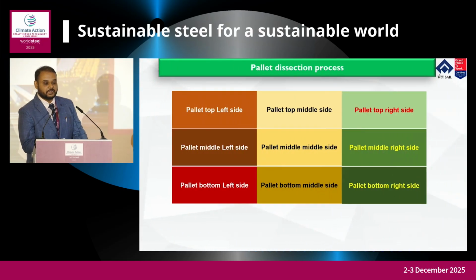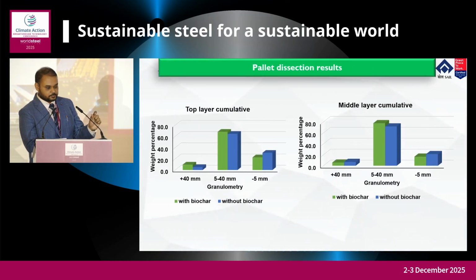And this is a unique study we have conducted. We lifted a fully ready pallet with biochar as well as without biochar, and compared these two pallets with a side-by-side size analysis. We segregated this into 9 compartments, both horizontally as well as across the width of the machine. And the result of this Sinter granulometry, that is, what percentage of +40 mm, 5-40 mm, -5 mm from each layer, has been compared with biochar and without biochar.